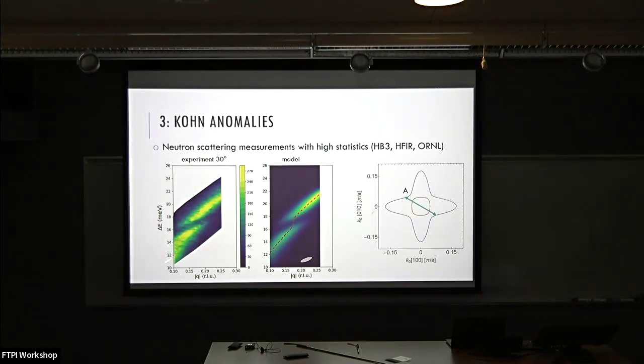So this is what it looks like. On the right is just a simple, again, very stupid model just to show. Basically, you get this fall because of the resolution. The actual phonon dispersion is convoluted with the resolution ellipsoid. That's where this minimum comes from. So this was just to show the effect of that.